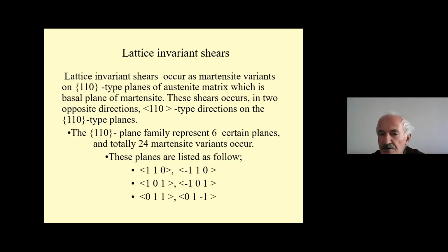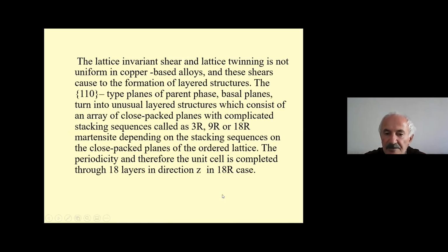Lattice invariant shears occur as martensitic variants on 110 type planes of the austenite matrix, which is the basal plane of martensite. These shears occur in two opposite directions, the 110 type direction on the 110 type planes. The 110 plane family represents 6 certain planes, and totally 24 martensitic variants occur. These planes are listed as follows: 110 minus 110, 101 minus 101, 011, 01 minus 1.